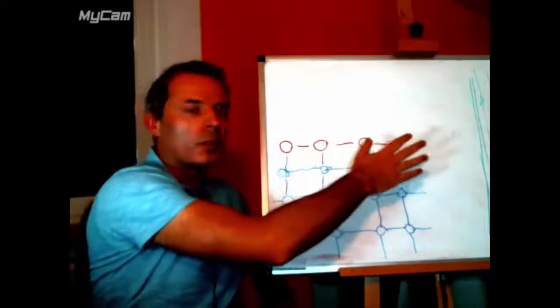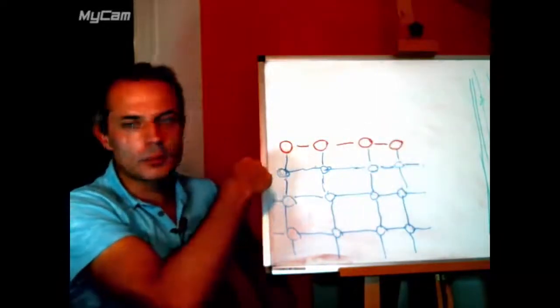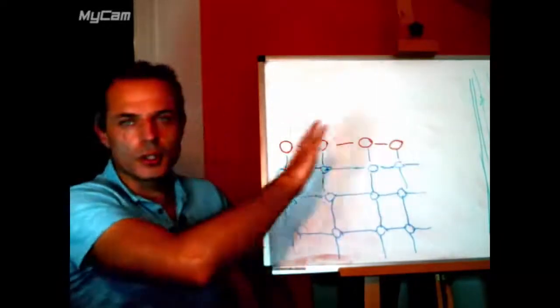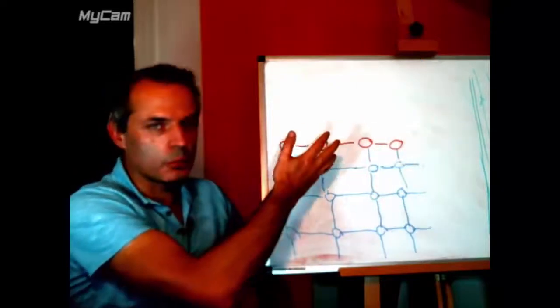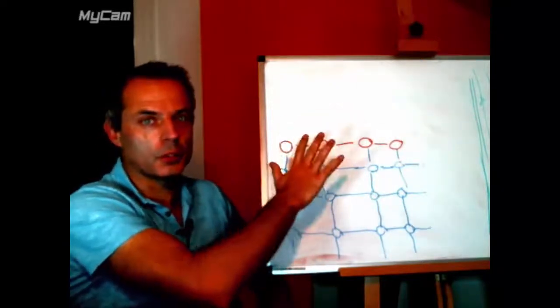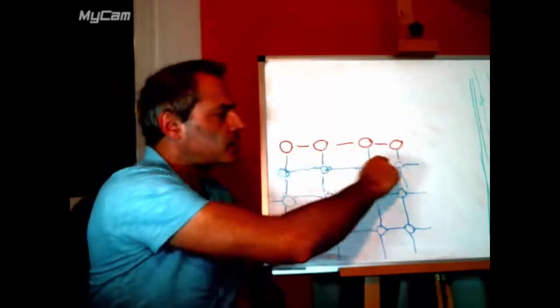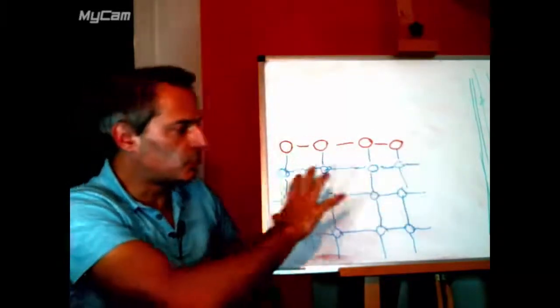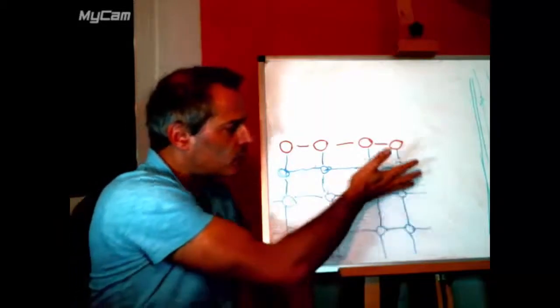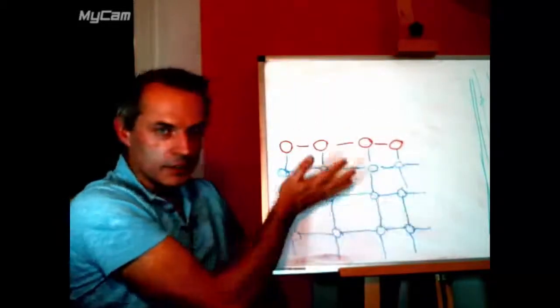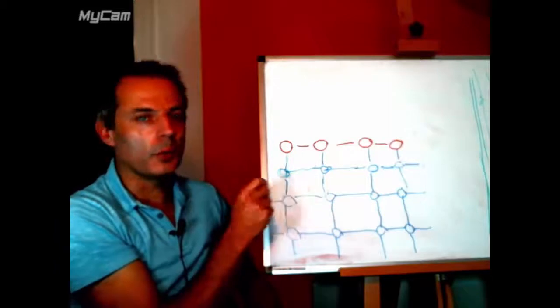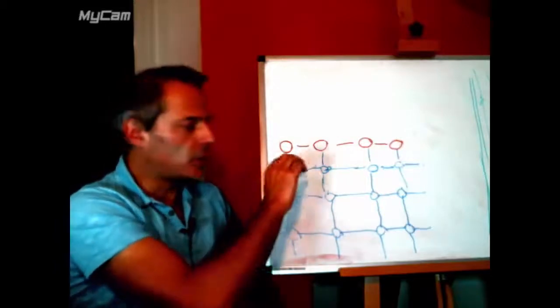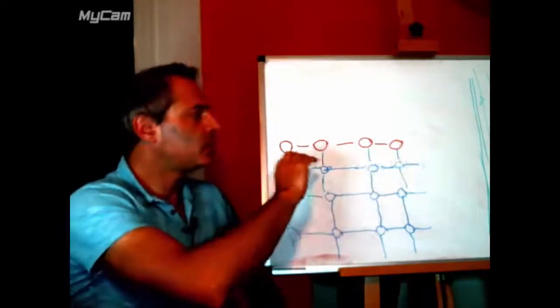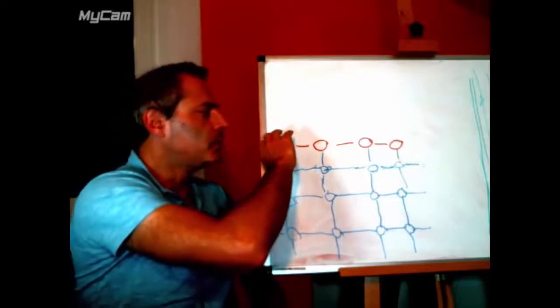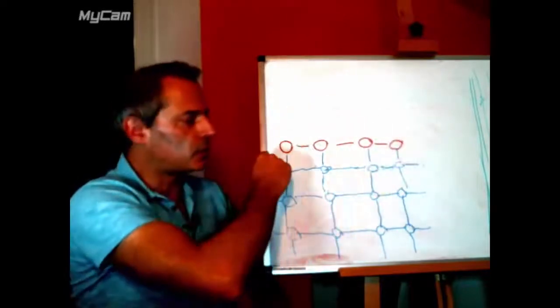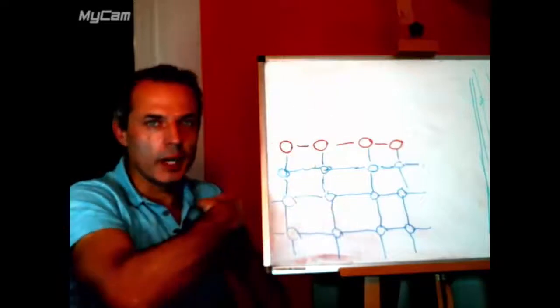We've got rid of it by adding a layer of these red atoms to the top, which has now closed the surface. There are no extra bonds left over, dangling bonds as we mentioned before, and that has made the rest of the lattice be able to relax, which has got all of the strain energy out of these other layers down below. So that's one way where a single layer of a new material on old material can actually be very easy to put on because it reduces the strain, so we get all of this energy back.